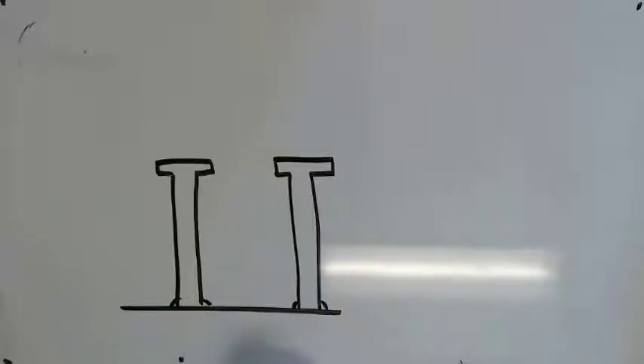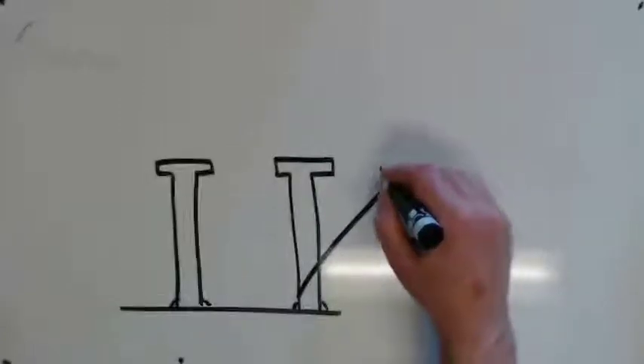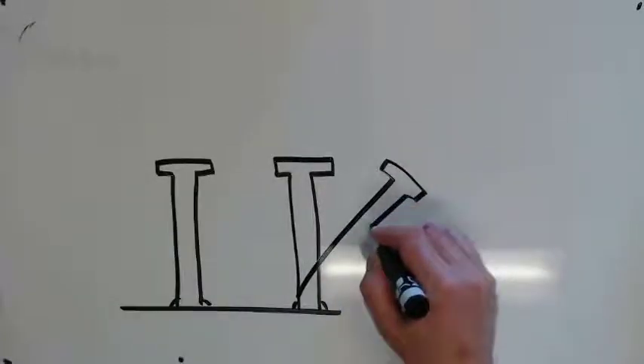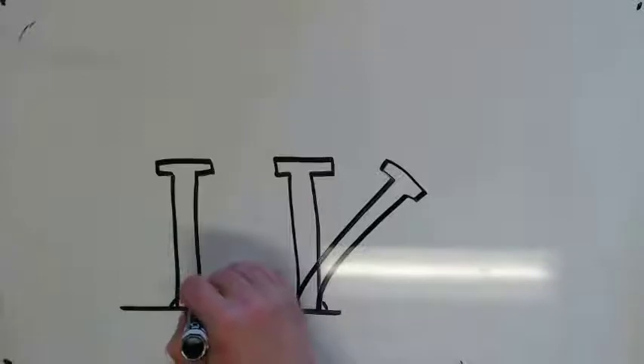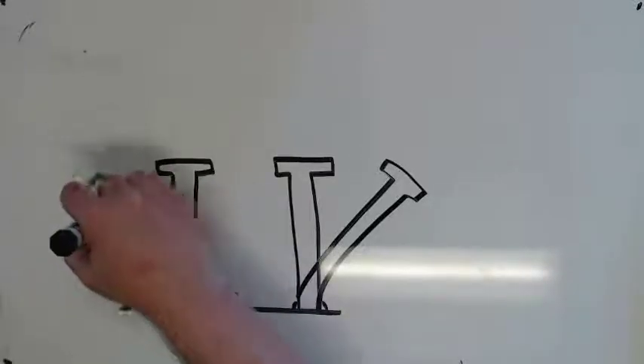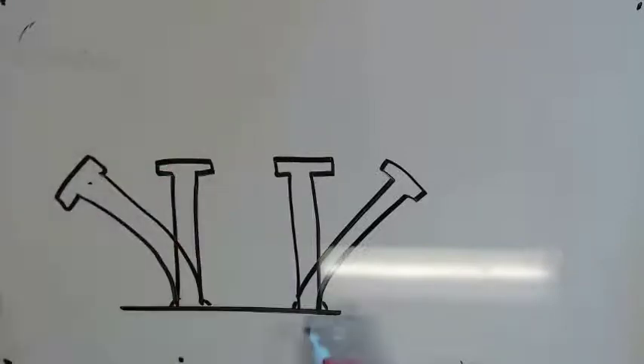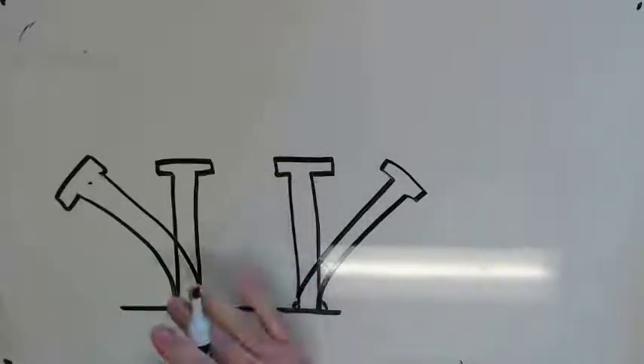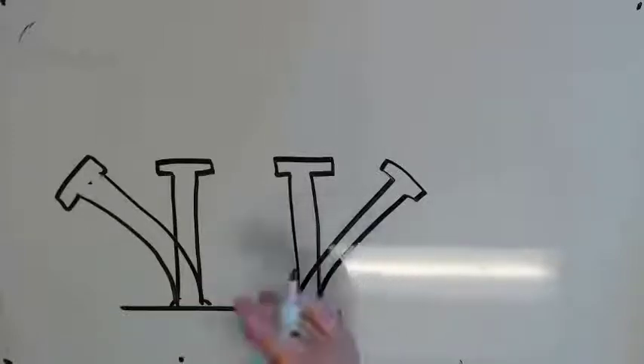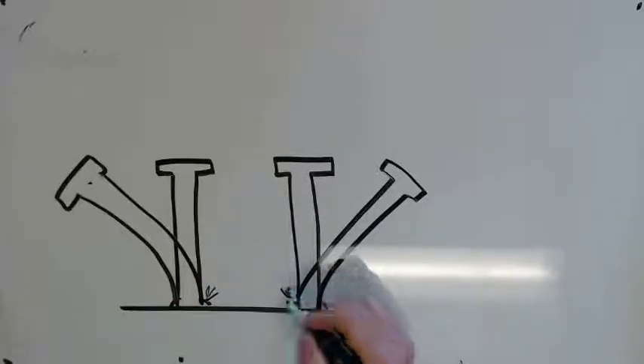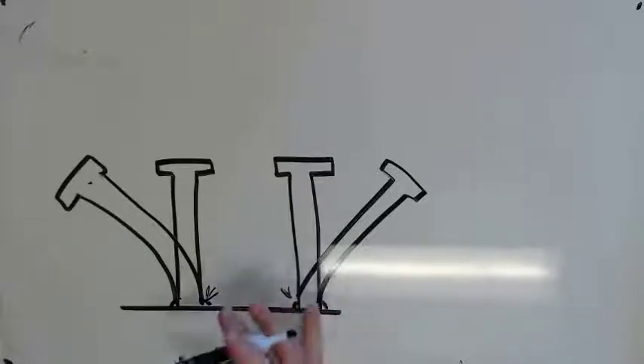And then you bend them over at a 30 degree angle. You're going to take these and bend them over at a 30 degree angle. And if you can bend them to 30 degrees, either by beating them over with a hammer or getting a cheater bar and pulling on them. You can bend them over 30 degrees. And the welds show no sign of lack of fusion or cracking here or here. Everything looks fine. You actually don't even have to fix them. You can leave them bent and continue on. But you have to do that at the beginning of every shift.